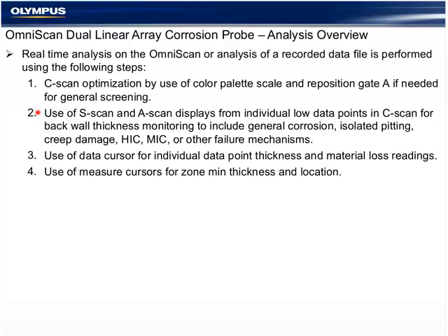We're going to use the A-scan and S-scan for individual data point analysis from a color pixel in the C-scan. We're going to use the data cursor for individual data point thicknesses and material loss readings. And within the cursors on the C-scan, we will create a zone for zone minimum thickness and location.